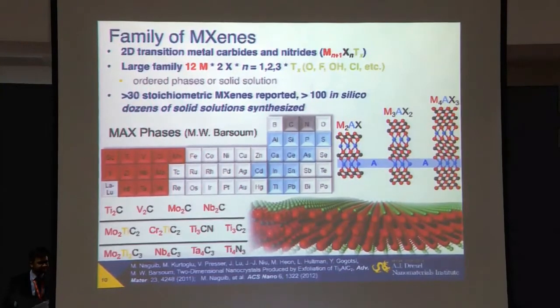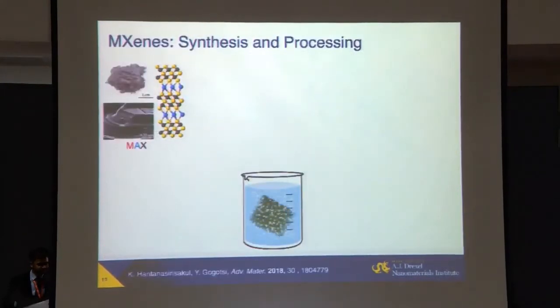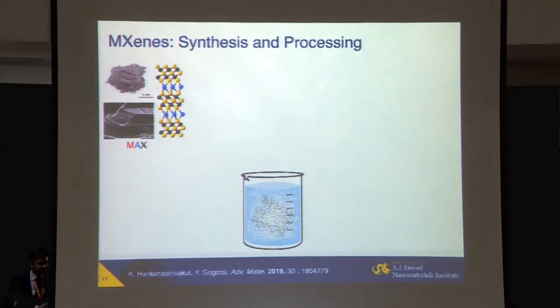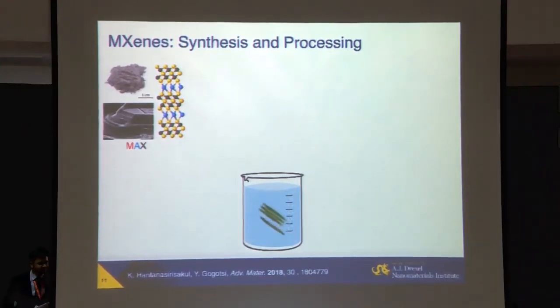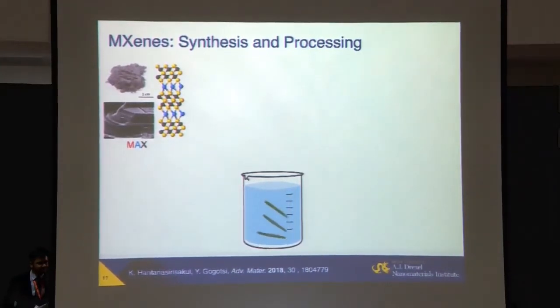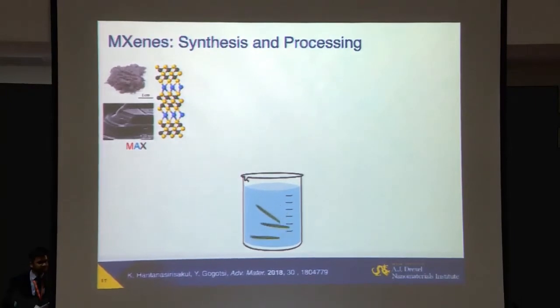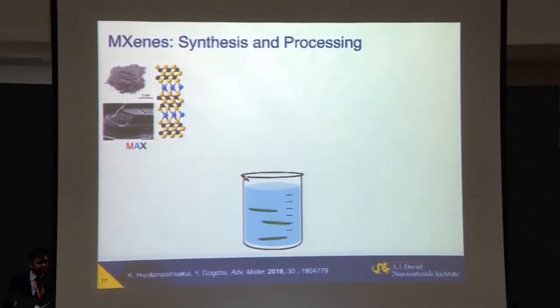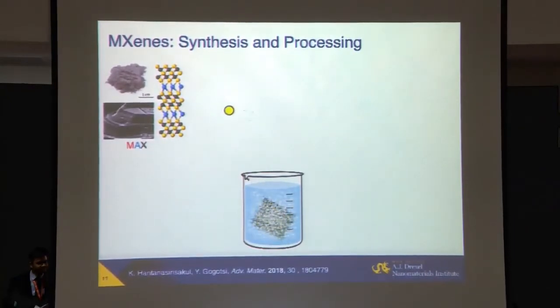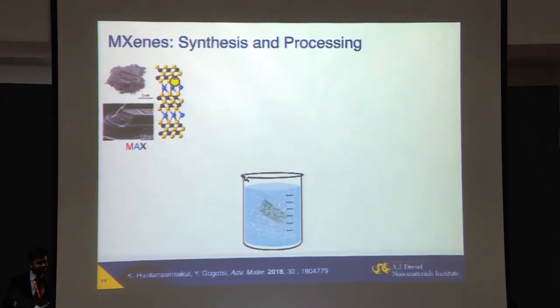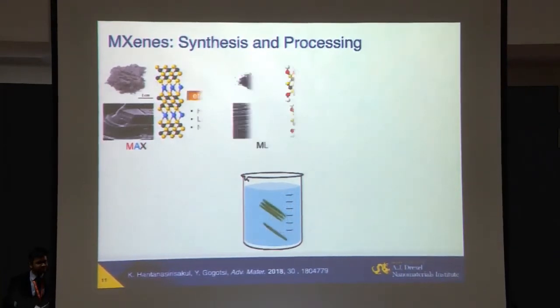And as a result, all these materials were produced. So we take ceramic powder, dump it in solution. Initially we use HF. Now we can use a variety of different etchants. We can etch electrochemically. We can etch in molten salts. And these A-element atoms, the blue ones, get dissolved.